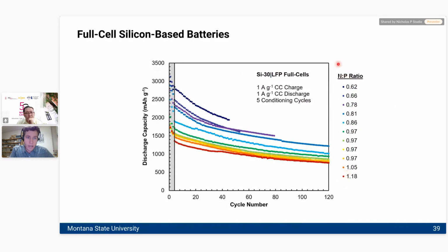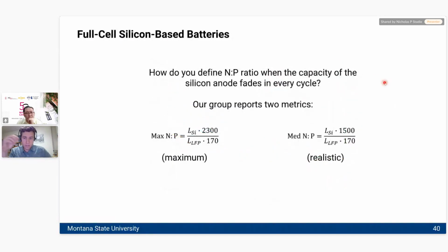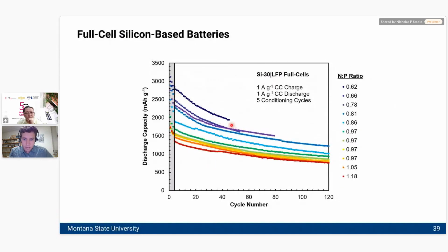It's very difficult to actually define this ratio, and so I'm going to show you at least one slide on why this is such a weird metric to calculate for silicon. The problem is, if your silicon capacity is fading so much on each cycle, you're actually changing the relative capacity for silicon on the anode side as compared to the cathode side in each cycle. And so, how can you define a single metric that relates to the cell balance? It's basically not possible with a material that's not very stable.